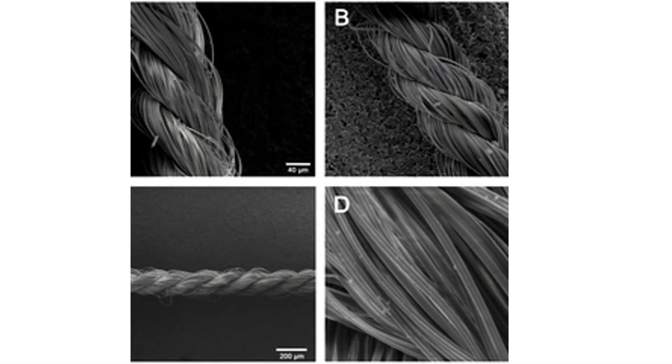Third is surgical techniques, and in particular, sutures. Currently, sutures' mechanical properties decrease over time and allow for an amount of infections to occur. Sutures made with the braided strands of spider silk exhibit the same amount of tensile strength as previous sutures, but have a high fatigue behavior, meaning they do not lose strength after having force applied on them multiple times over time. Spider silk uses all of its properties expertly as webbing. One of its great properties is that it's made of protein, allowing spiders to eat and recycle it within their bodies to transfer that protein towards a new web. However, there is no such process yet to mimic this recyclability when used in the processing of clothing, military wear, or sutures.